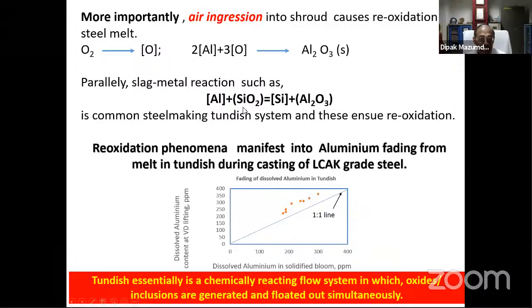Parallelly, you have dissolved aluminum, and if air ingression does not take place, then we have Tundish powder, which contains silica. Silica is a less stable oxide. Aluminium reacts with silica. There's a slag metal reaction, as a result of which alumina is produced. So the alumina can be generated in steel, and as a result the cleanliness of steel can be impaired in the Tundish. So these are the reoxidation reactions.